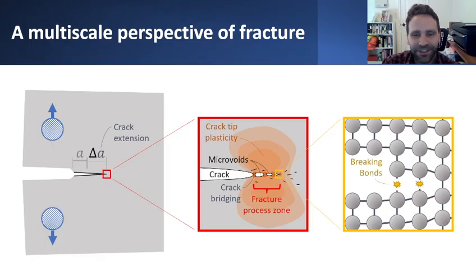But clearly there's a lot going on in this region, going from crack tip plasticity to micro crack development to micro void growth and eventually coalescence of these microvoids into crack extension. And this whole process really indicates that it's not as simple as just the crack extends. It's not that there's either a crack there or there's not. Really, the line between fractured material and totally unfractured material is very blurred. And this zone of material where all these interesting things are happening is sometimes called the fracture process zone, giving some kind of definition to this thought that fracture is not just an instantaneous thing.